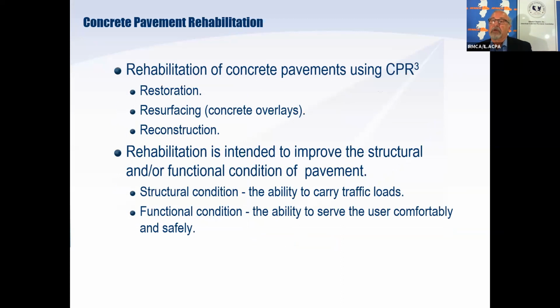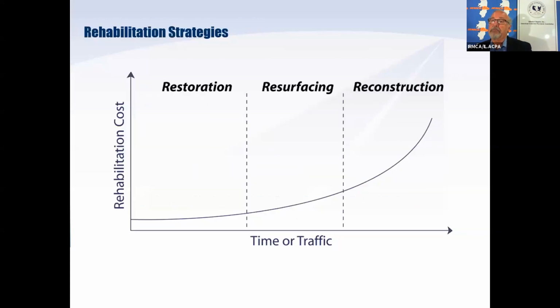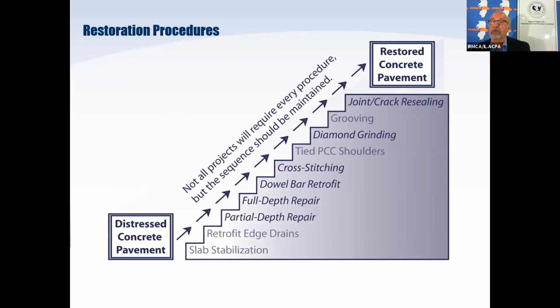So rehabilitation, again, is what we are typically going to look at up front. And so this talk is going to talk about restoration techniques as well as resurfacing. The restoration procedures we typically would look at start off on the lower left and go to the upper right. If we have voids under the slab, we have visible areas where the support conditions are less than adequate for the pavement, we might do slab stabilization, where we inject a material underneath the slabs in place to restore load transferabilities, to restore the uniform support under the slabs, which is what we're trying to get.